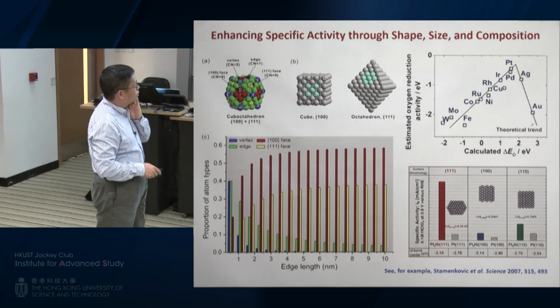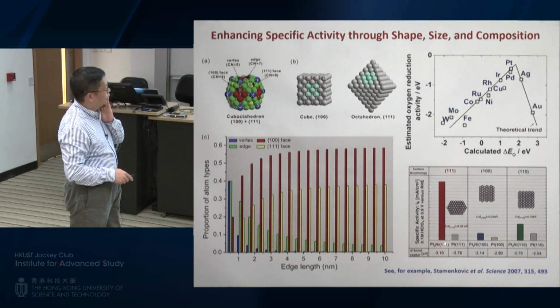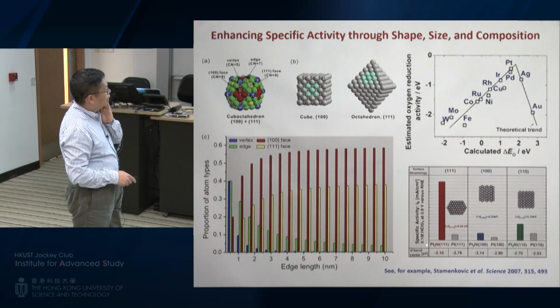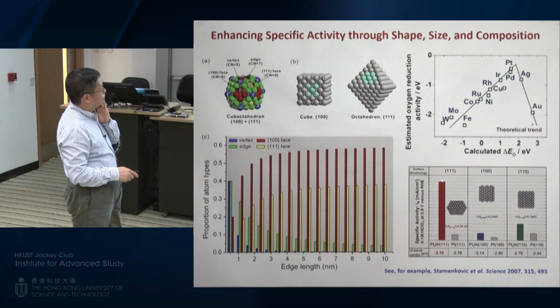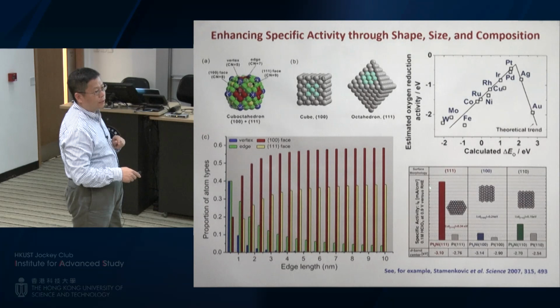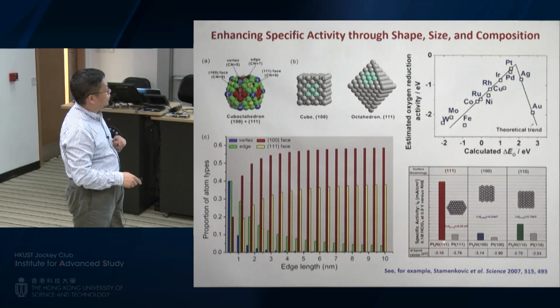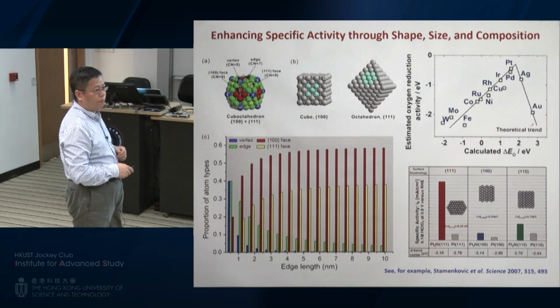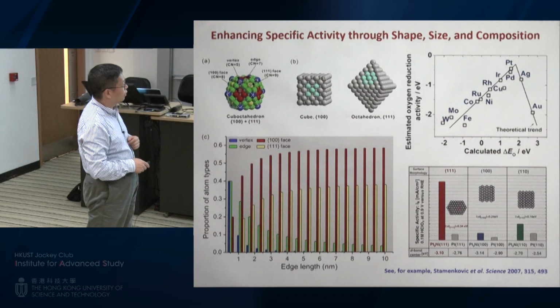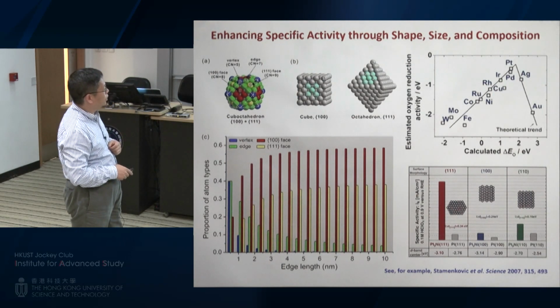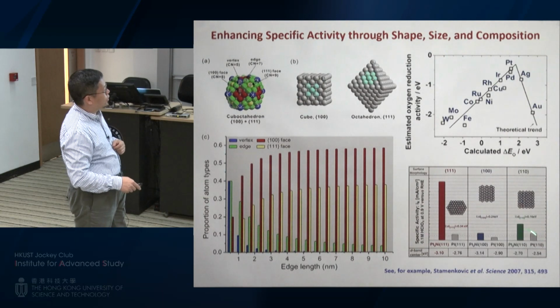And composition is also important. You can form alloys, like shown over here. You can have Pt nickel if you can mix them to form alloys. And you can see this specific activity could be increased very dramatically, actually. This is compared to platinum 111. This is Pt nickel 111. It could be increased by almost 15 or even 20 times, in that kind of range. So that's basically the results based on single crystal substrate measurements.